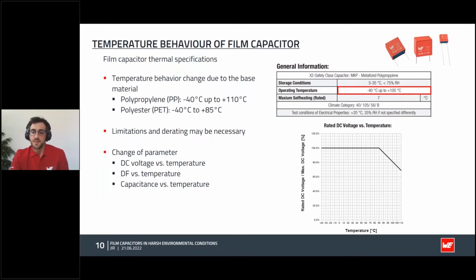Now let's see the temperature dependencies of capacitance and dissipation factor in film capacitors. Going over 110 degrees Celsius will irreversibly damage the polypropylene capacitors. And that is the reason why SMD film capacitors are not very common and present many challenges during circuit assembly and solder process.